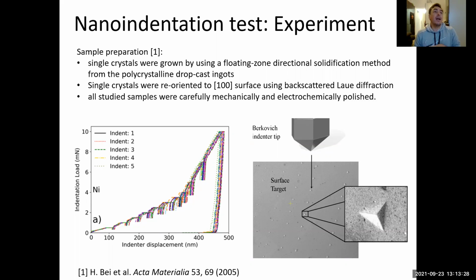And here I'm presenting the results that they obtain from the experiments when they do the nanoindentation. They have this typical graph called the load displacement curve, and here we get all the information about the mechanical properties of the material. Really, the nanoindentation test on these materials is a non-invasive technique. If you are doing a tensile test, it is really invasive and destructive. With nanoindentation, it's better to test the mechanical properties. It has some advantages and disadvantages over the tensile test, but it is a good way to test the mechanical properties of a material.